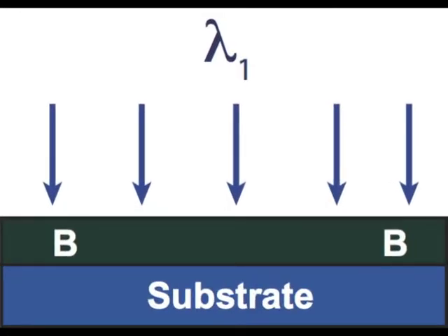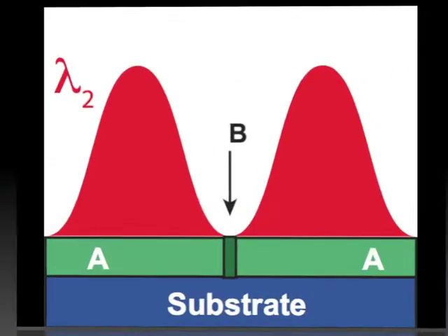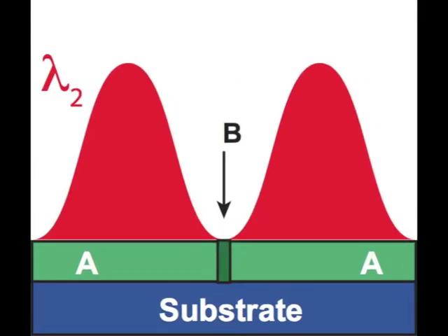In POST, a thin film of organic photochromic molecules is thermally deposited onto the surface of a substrate. The molecules are then excited uniformly with lambda-1, rendering them reactive. Next, patterns of intensity minima of lambda-2 are used for photoswitching molecules from state B into state A with distinct spectral properties. Following a saturated photoswitch into state A, only at the nodal point is the molecule confined to state B, which is then locked in to write the nanostructure.